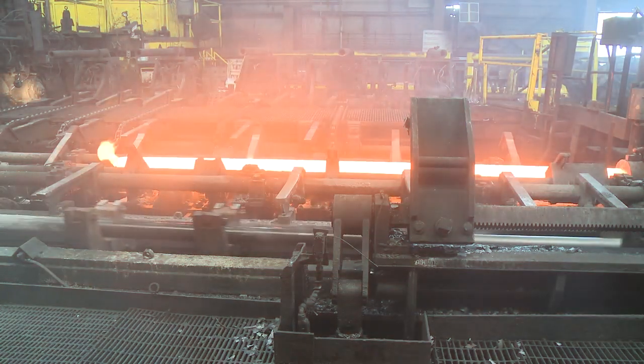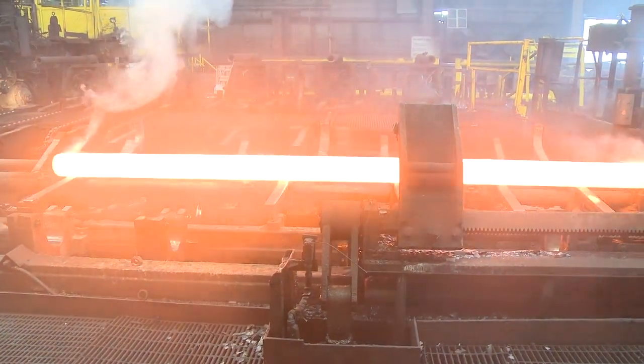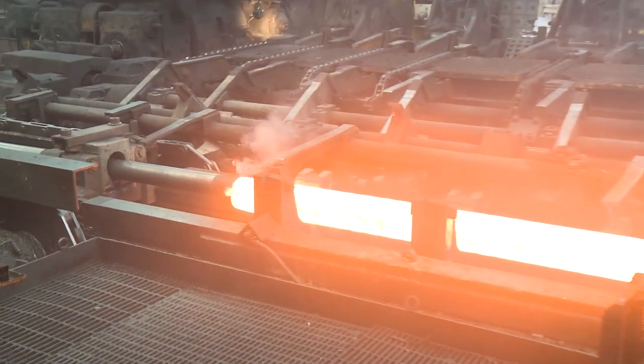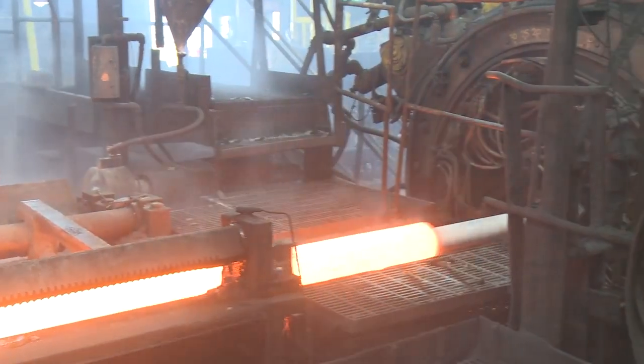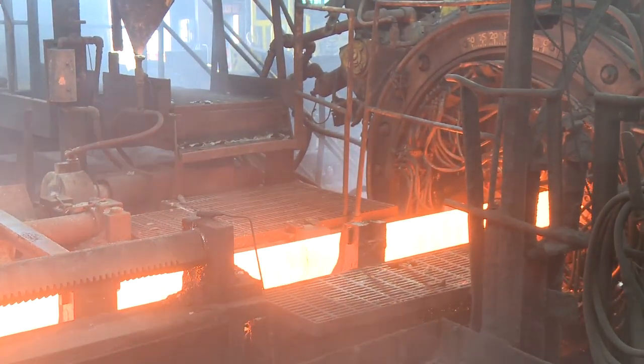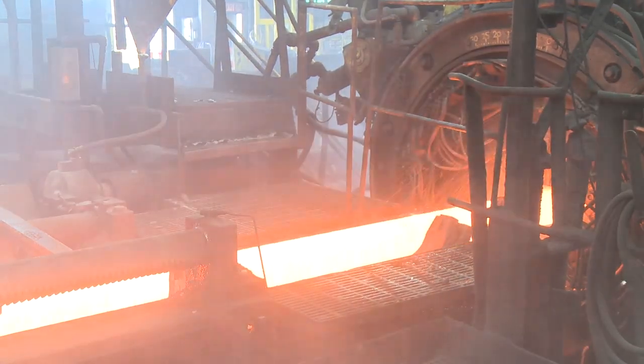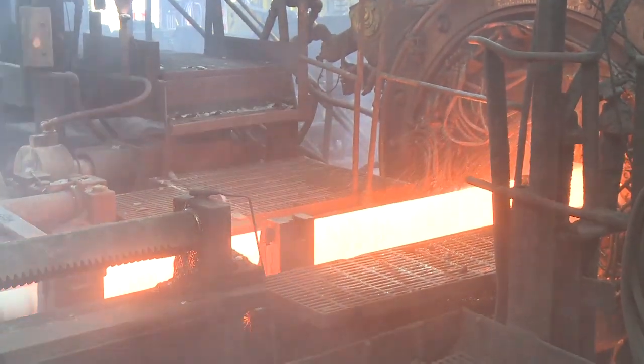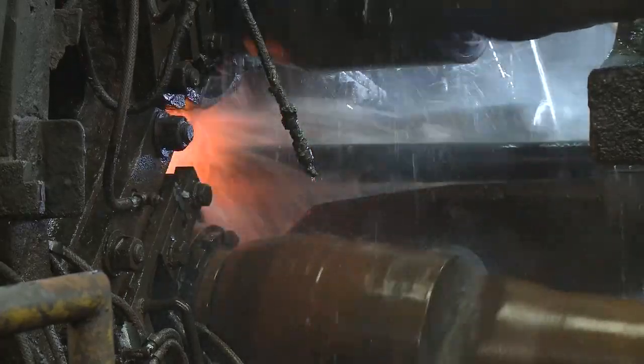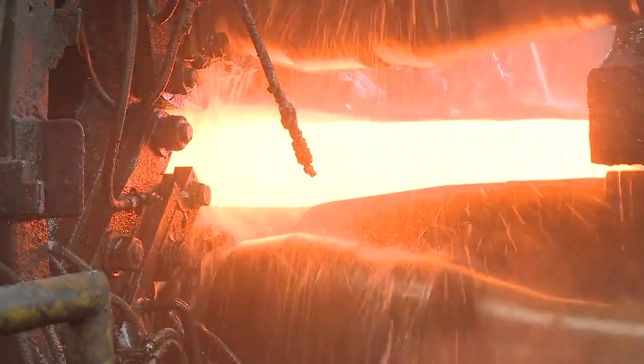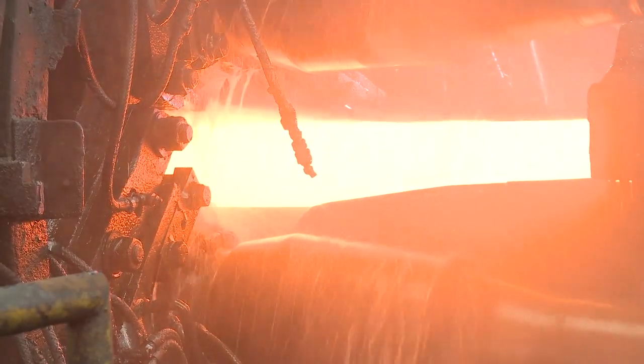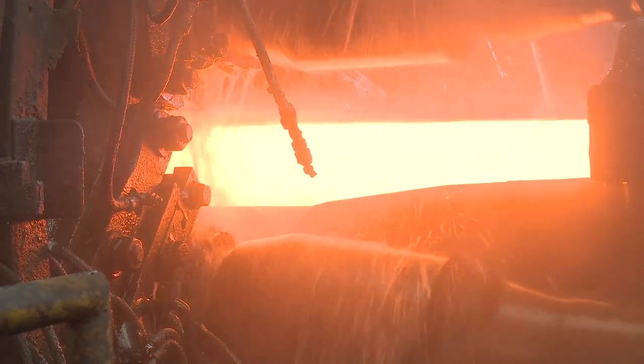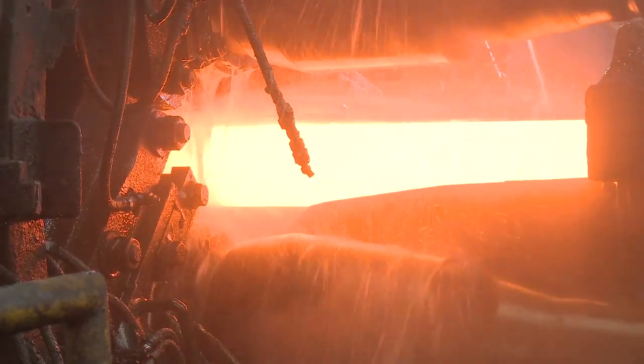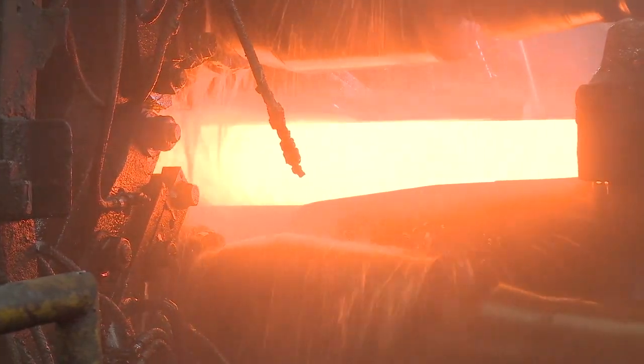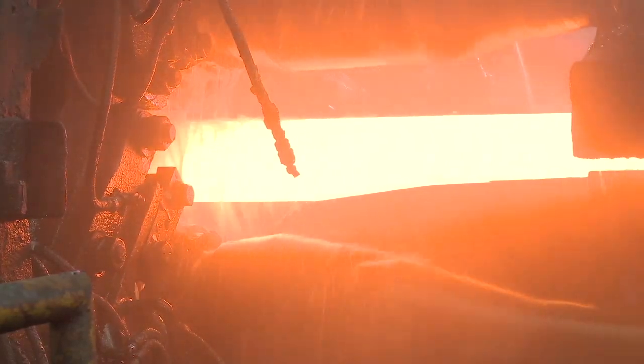Our number 5 tube mill uses an elongator mill to form the proper wall size for the customer. Wall size for the elongator mill runs from 0.430 inches up to 2.5 inches in 1/1000th of an inch increments. The cross-rolling action of the OD, forcing the hot shell down onto a mandrel bar on the shell inside, produces a smooth inner diameter surface and a precise concentricity along the tube's full length. The elongator also has the ability to skew or quickly open the work rolls. This allows the mill to process an OD to wall ratio up to 13:1.